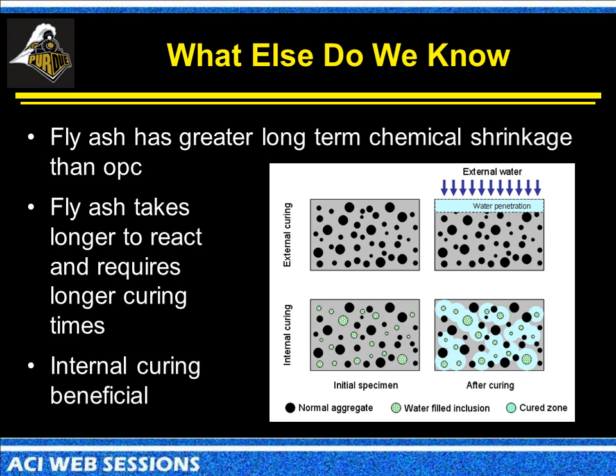Once the mix is set, we've essentially locked in the porosity of the system. At that point, we start to develop that underpressure in the fluid because of the chemical shrinkage that's driving this, and that actually pulls the curing water out of the lightweight aggregate. You hear a lot of people talking about smart materials. This is kind of one of the original smart materials. Exactly when the water is needed, it's going to be pulled out of the lightweight aggregate, and it's going to allow you to have continued hydration taking place inside of the overall system.